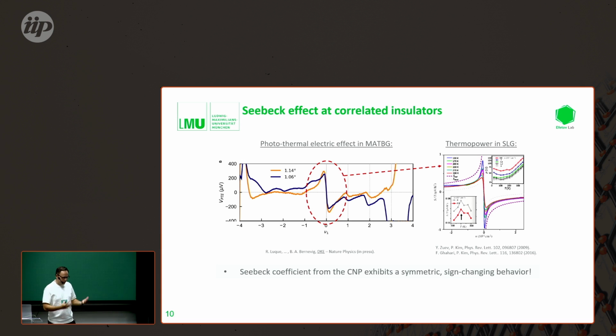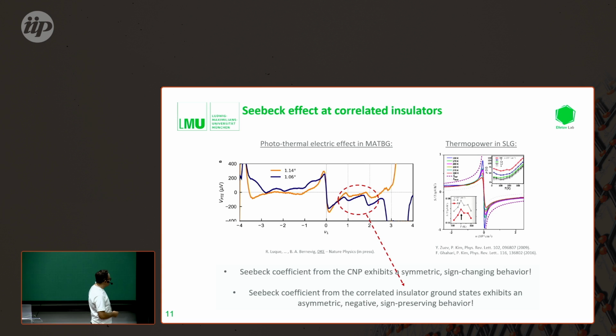So this behavior resembles the symmetry between electron and hole excitations, and gives you also the right sign of the Seebeck effect. However, as I mentioned before, also at filling factor 2 and filling factor 1, we actually have gaps. We have electron-hole transitions that we can study in transport, for example. However, you see the signal is very different. The two things that are different here are, first, we do not have a sign reversal, but actually always keep a negative photovoltage here. And second, across the transition the signal is very strongly asymmetric.